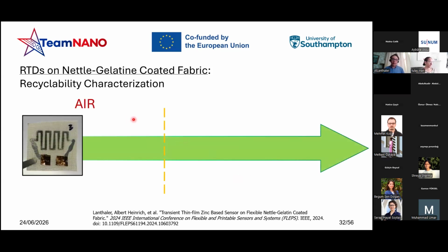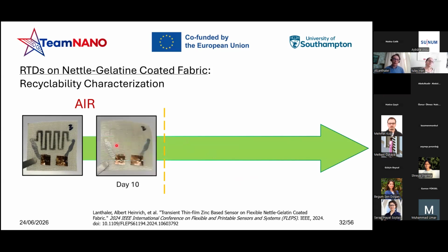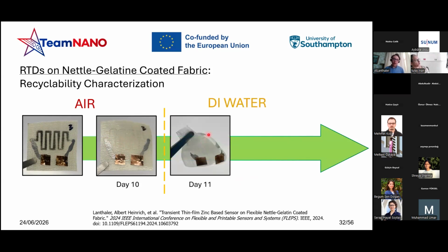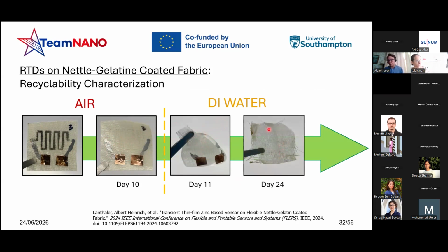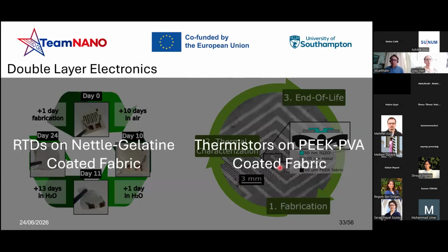We were actually able to see a fully recyclable device as we wanted, a transient device. So within 10 days, we have the device completely absorbed by the gelatin itself, keeping it trapped into and sealed into the very substrate, meaning that we are able to perform a DI water-based recyclable process, dipping the full device into it, and within 24 days, we are actually able to reuse the whole platform itself for a second round of electronic deposition.